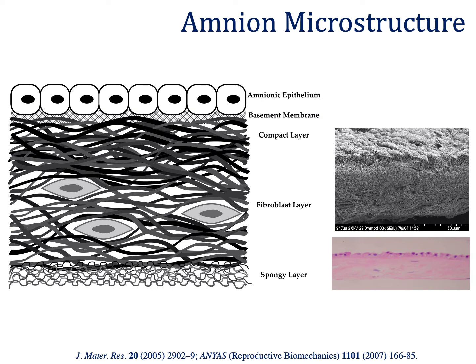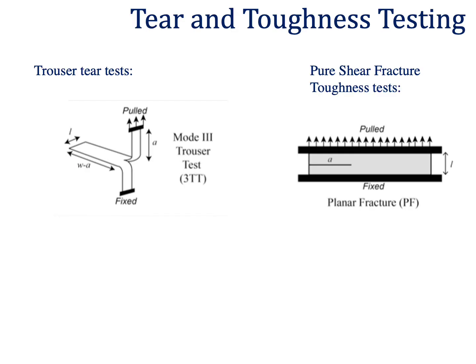Now, because we want to study the process of fracture of this membrane at the time of birth, we have been conducting a series of tests where we've been studying tear and fracture toughness using a couple of different geometries. So we've been using a trouser tear test, which is exactly as it sounds and as it's depicted here. It's like how you would tear a piece of paper by pulling your hands in opposite directions. And we've been comparing this to a more mechanically rigorous pure shear fracture toughness test in which you grip a small section of tissue relatively close in the grips and then introduce a notch and propagate that notch.